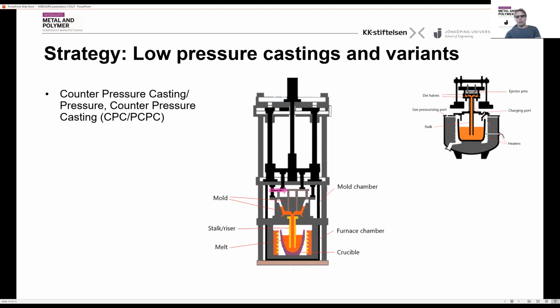And you can work then with the pressure difference between the furnace compartment and the die compartment. And this again is to control the fill. And that means also that by varying the two pressures, you can also control the speed during filling, because speed during filling is essential for all these casting processes. You can take the next.